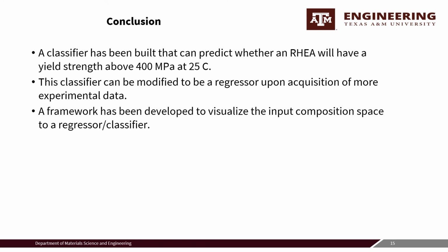In conclusion, while the regressor models failed to meet our specifications, primarily due to a lack of data, a classifier was successfully built that can predict whether a refractory high-entropy alloy will have a yield strength above 400 megapascals at 25 Celsius. This classifier can be modified to be a regressor whenever more experimental data becomes available.